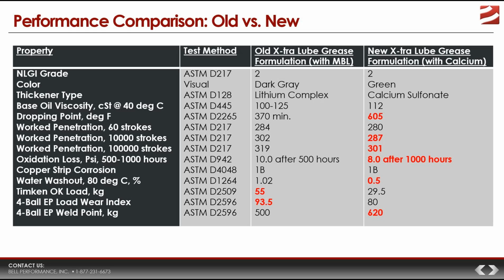So what happened is that at 500 kilograms, the old grease's balls welded together, and they stopped the test. When they tested the new X-tra Lube Grease with calcium sulfonate, they ran the test all the way up through all those load increments and got up to 500. When they got up to 500, the balls didn't weld — they were able to keep going. The next load specified in the test parameters is 620, so they ran it at 620, and the balls welded together. So the actual weld point was somewhere between 500 and 620.